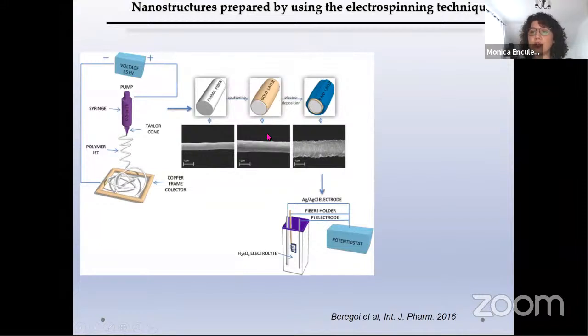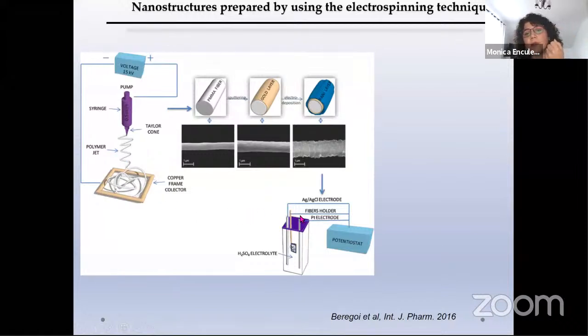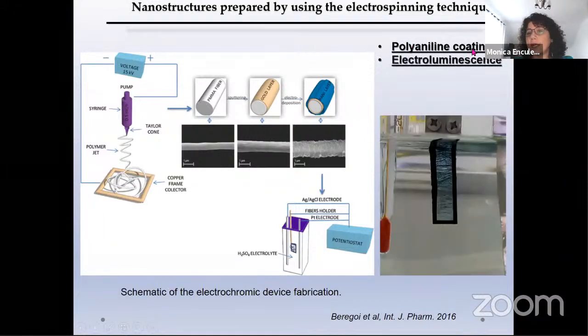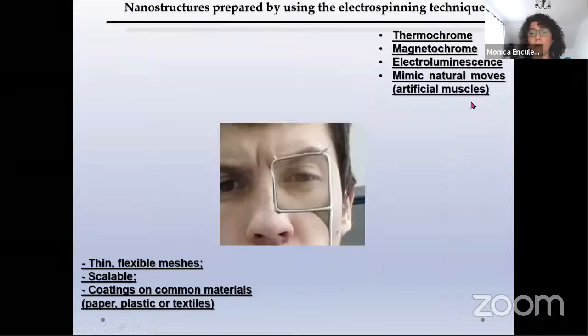This allows the conduction of this type of fibers. And because they are conducting, we can use them for electrochemical deposition. And in this way, putting them in an electrochemical bath on this frame, we can obtain the covering with, for instance, polyaniline. And polyaniline coating can give us the functionalities of electroluminescent type of material. So in this way, because we can collect those type of structures on a frame, we obtain thin, flexible meshes.